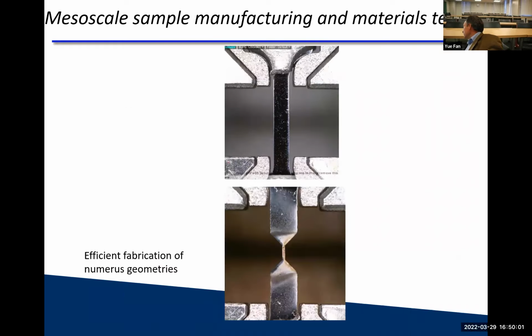And recently, we started to make more tensile tests. So this is SSJ2 tensile geometry. They are 1.2 millimeters wide. They're the standard nuclear reactor tensile test samples. But now we use these very same ones and cut small samples in those bigger ones to really try to understand the relationship between sample dimension and property, and that they're not independent from each other.